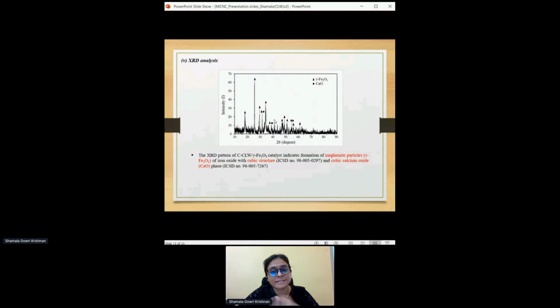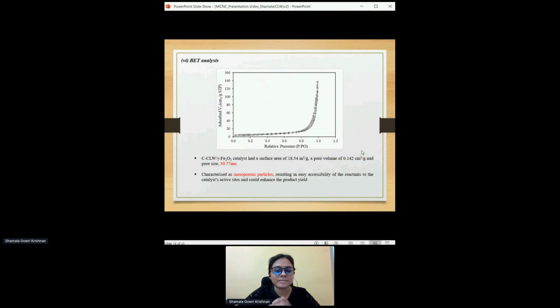This was confirmed when we did XRD analysis, where we found the formation of maghemite particle, which is the iron oxide formation in the cubic structure, followed by the cubic calcium oxide formation. And this catalyst has a surface area of 18.54 meters square per gram, followed by the pore volume of 0.142, and it has a larger pore size, which is 30.77 nanometer, which explains the catalyst as a mesoporous particle, which helps the active site to be easily accessible for the reactant and produce a high yield.